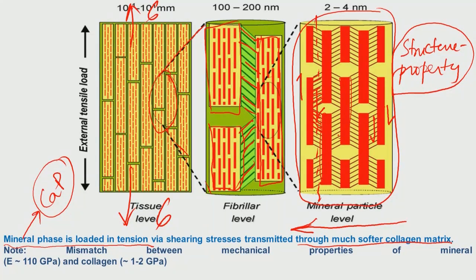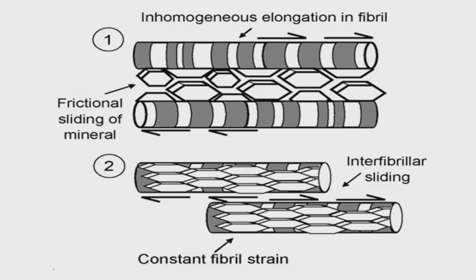And if you see the typical difference in the elastic modulus values, the elastic modulus of collagen is 1 to 2 gigapascal, which is an order of magnitude less than the elastic modulus of hydroxyapatite. Hydroxyapatite elastic modulus is 110 gigapascal, collagen elastic modulus is 1 to 2 gigapascal. Because of this large mismatch in the elastic properties, it is quite feasible that hydroxyapatite will be loaded in tension and collagen will experience more of a shear stress under mechanical loading.